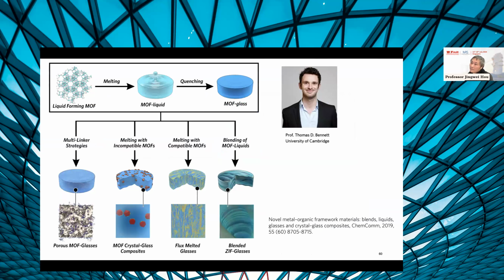I mean, depending on what you are trying to melt the MOF with, because if you look at the temperature of the MOF melting itself, typically we're talking about 300 degrees, 400 degrees-ish. So that means it is quite thermally challenging, but that's not the whole story, because once the MOF is melted, it's behaving something similar to an ionic liquid. It's highly reactive. So a lot of materials will not survive the high temperature treatment or co-melting with MOF. So that's maybe the bad news.